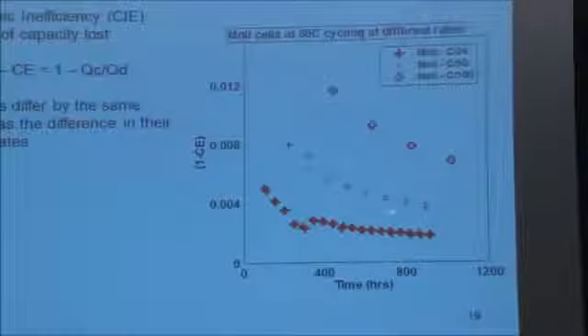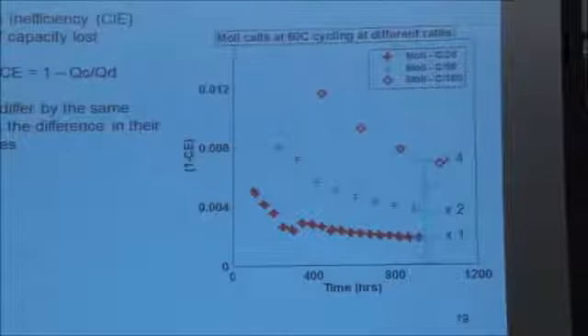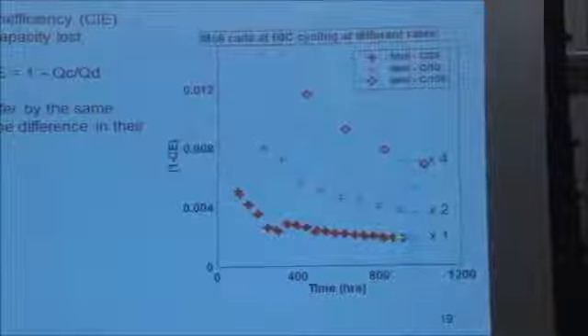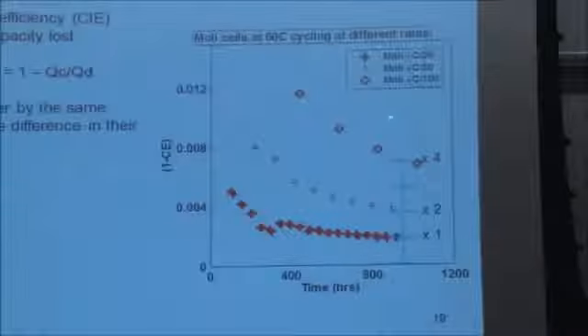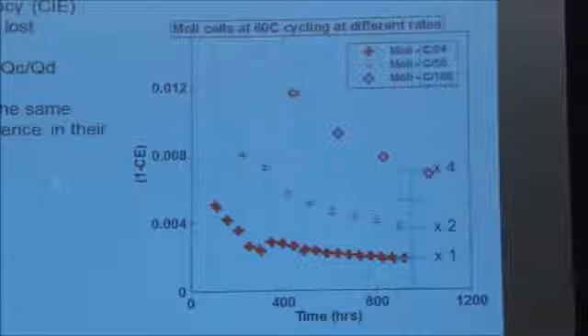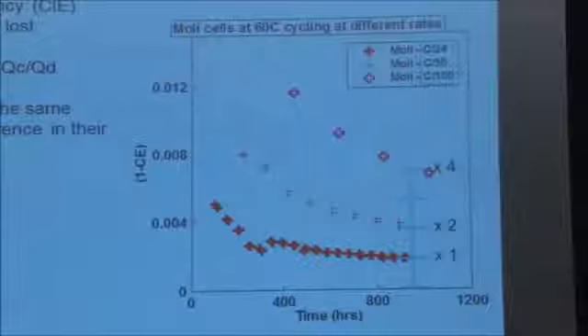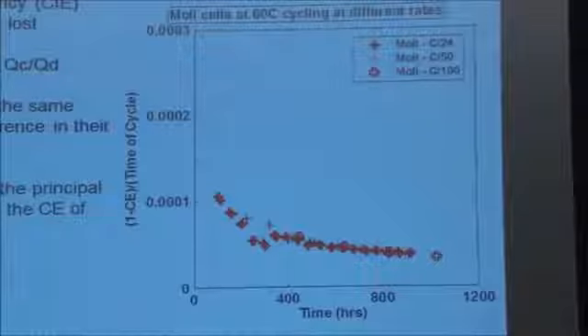And if you instead plot the Coulombic inefficiency, which is 1 minus the CE, so just flip the data over, and then take a look carefully, you'll notice that the Coulombic inefficiencies scale 1 to 2 to 4, just like the cycle times do. And if you divide 1 minus the Coulombic efficiency by the time of a cycle, all the data falls on a universal curve. Okay, so it's telling you that time of exposure is really the bad actor here in the failure of these cells at elevated temperature.